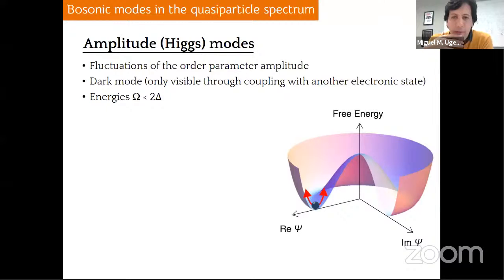So another more serious candidate could be the existence of amplitude and Higgs modes in niobium diselenide. Basically, an amplitude or Higgs mode arises from the fluctuations of the order parameter amplitude. So the amplitude of the superconducting order parameter can fluctuate, and that leads to the emergence of some collective mode in the density of states, or in principle visible in the density of states.